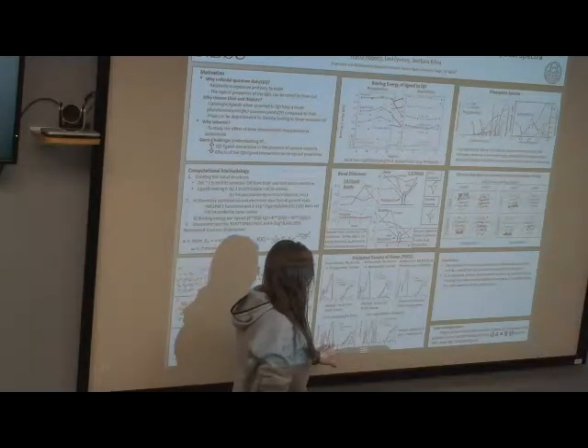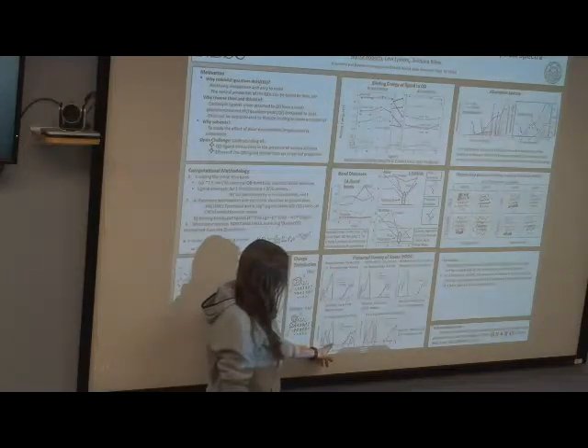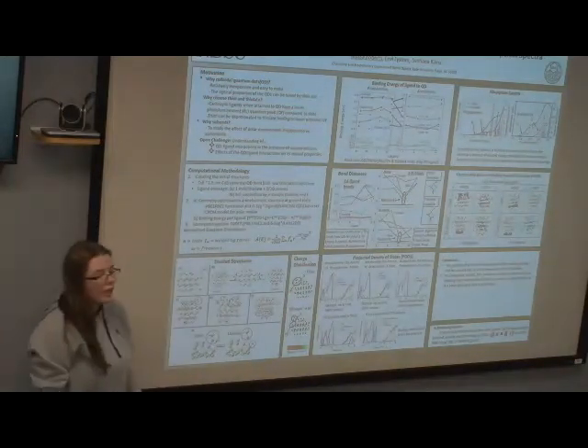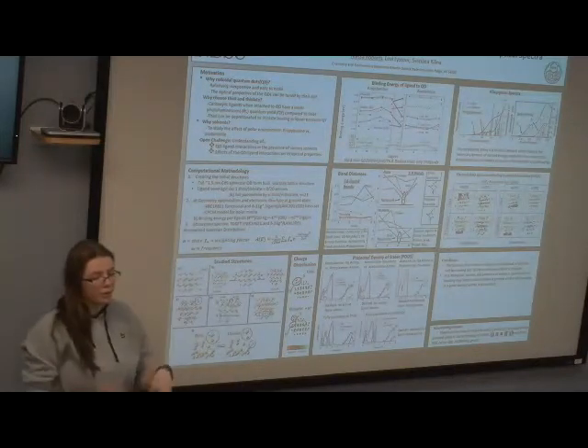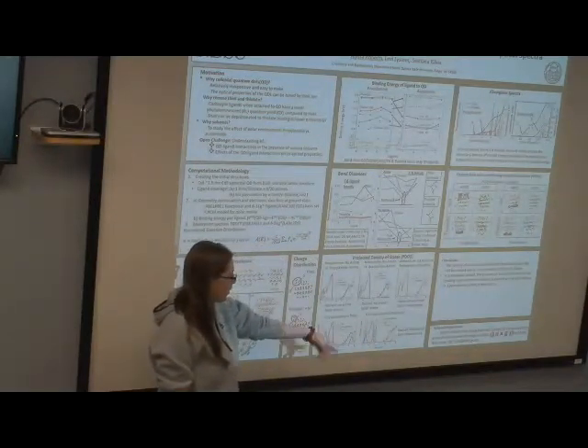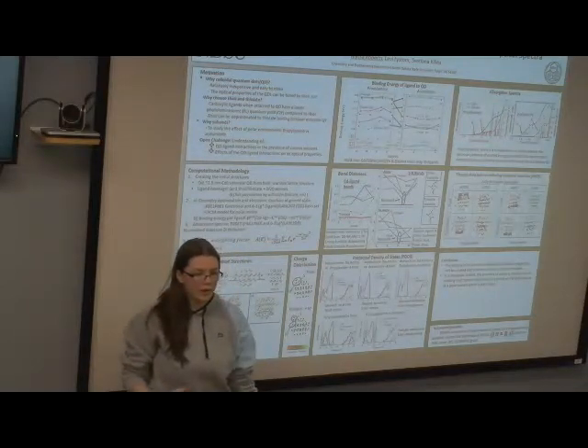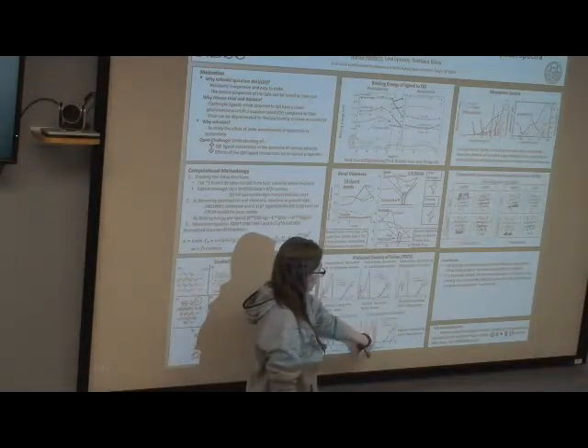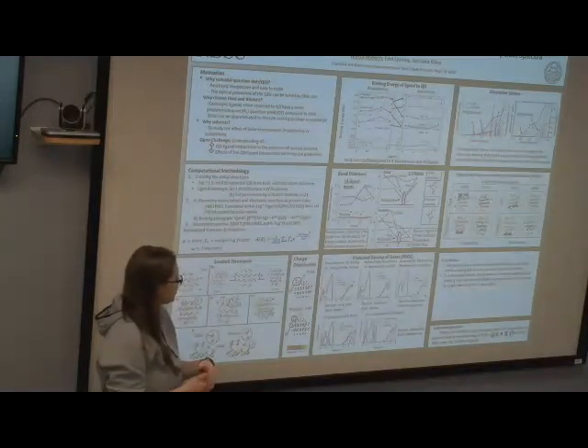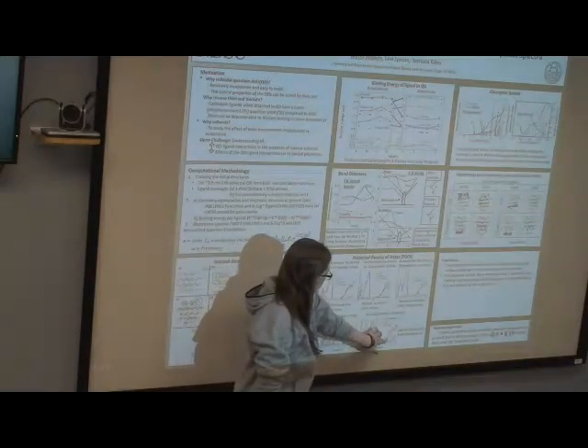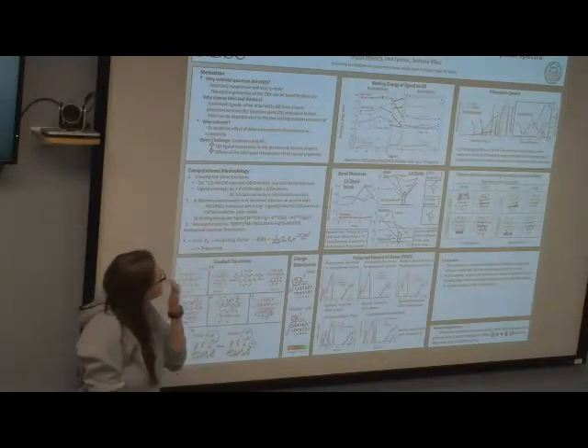And you can see that in propylamine, the thiol is closer to the quantum dot, and in acetonitrile, it's moved back slightly. Which means that the optical properties could potentially be better in the acetonitrile for thiol than in propylamine. However, for the thiolate, the fully passivated thiolate with a proton, there is not a huge change whether or not it's in different solvents. The peak is significantly higher for acetonitrile, but I'm not really sure what that affects, but basically this could create a trap state, which would cause a decrease in the optical properties.